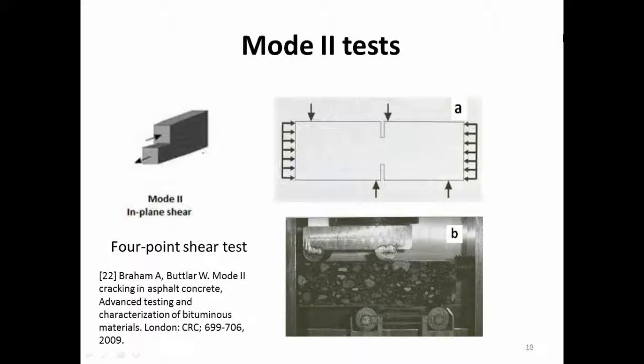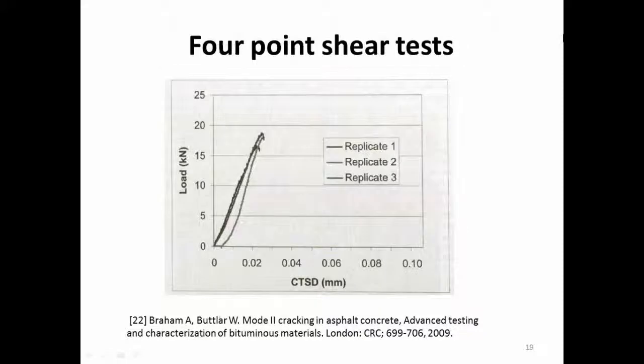So how about mode 2, the sliding one? There are not too many tests for pure mode 2, but one of them is called the 4-point shear test. Basically, you put a pair of loads here, but because of the position between these two, it can create a sliding effect in this middle part, and that helps to fail the specimen. So here are some of the representative 4-point shear tests.